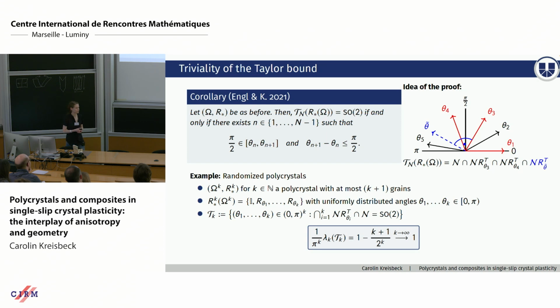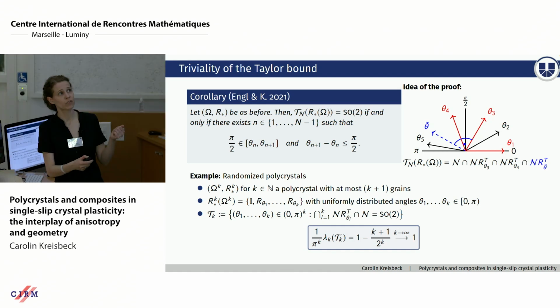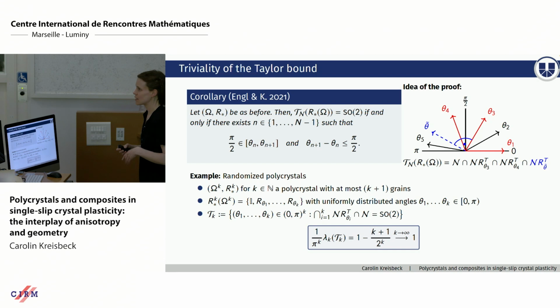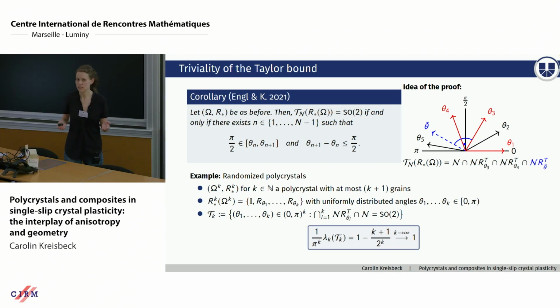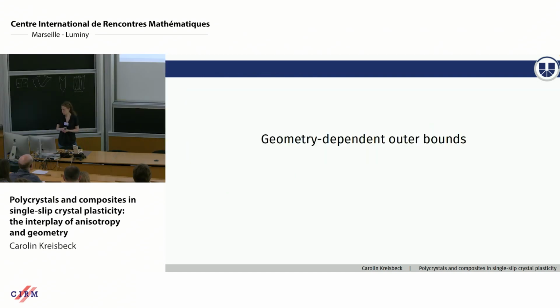So if we think of samples, so randomized polycrystals, crystals with a random orientation of the slip directions, we consider rotation angles that are uniformly distributed, and then we can calculate the probability of finding a trivial Taylor bound independent of the number of grains that we have. So the formula is down here, and you see as you let k go to infinity that for a large number of grains, it's very likely to find a trivial Taylor bound. So much for inner bounds.